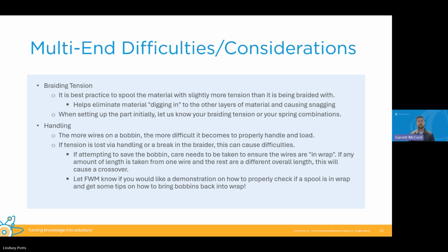And then also handling is a big consideration when ordering multi-end material. Generally, the complexity and the difficulty to handle goes up with the more wires you put on a bobbin, as well as whenever you increase the size along with that. So if tension is lost via handling or a break in the braider, this can cause some serious difficulties when trying to braid.